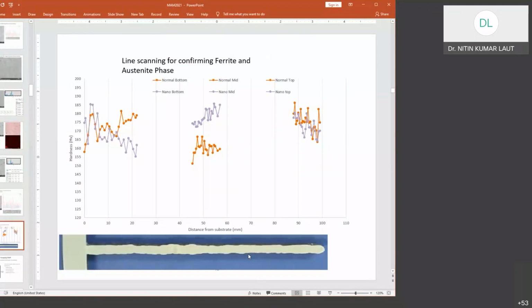Okay, so the space conformation is not that important. You can see if you try to analyze the material distribution or material characteristic at different points along the height of the developed specimen, so this is your z-axis, then you will find at the center, so you will now understand why we have chosen the sample at the central location, because if you see the two extreme ends, you will get a lot of variations here. But here you get clear-cut demarcation, specifically at the central layers, of the distribution of another property, a mechanical property, that is hardness. So you get better clarity of hardness variation, and the effect of addition of these nanoparticles in this CMT process.